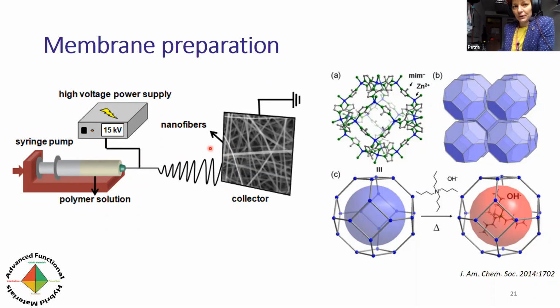But what I wanted to show is also that, of course, we wanted to demonstrate that this can still lend itself to highly hydroxide ion conducting materials. So for that we used a previous work in which they worked in the bulk, so powdered metal organic framework. They used this zinc-based metal organic framework called ZIF-8. Now what I would like you to focus on is that little grey dot there, which is a methyl group on the methylimidazole linker of the framework.